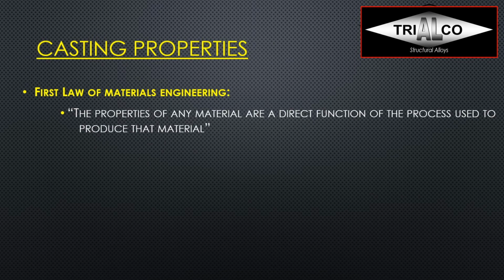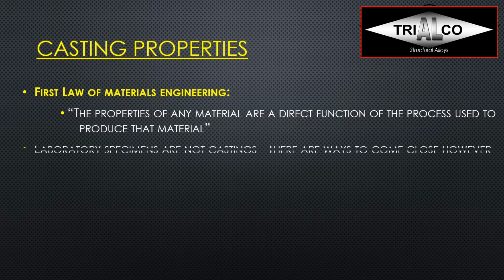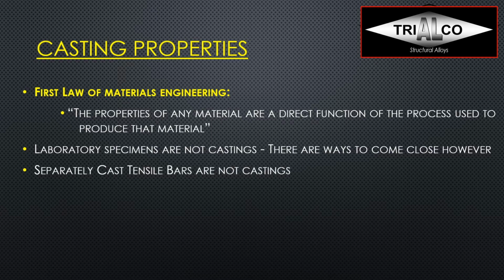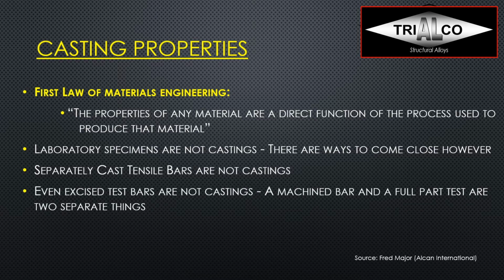So now let's have a look at casting properties. The first law of materials engineering is that the properties of any material are a direct function of the process used to produce that material. So it is very clear that laboratory specimens are not castings. There are ways to come relatively close to very similar properties, but it's not going to be the same. And separately, cast tensile bars are not castings either. You can simulate something relatively close to maybe somewhere in the casting, but it's not the casting itself. And even excised test bars are not a full casting. It's just one machined bar, and it's representative for that one specific region of the casting. You can't say those are the properties that I'm getting in the entire casting.